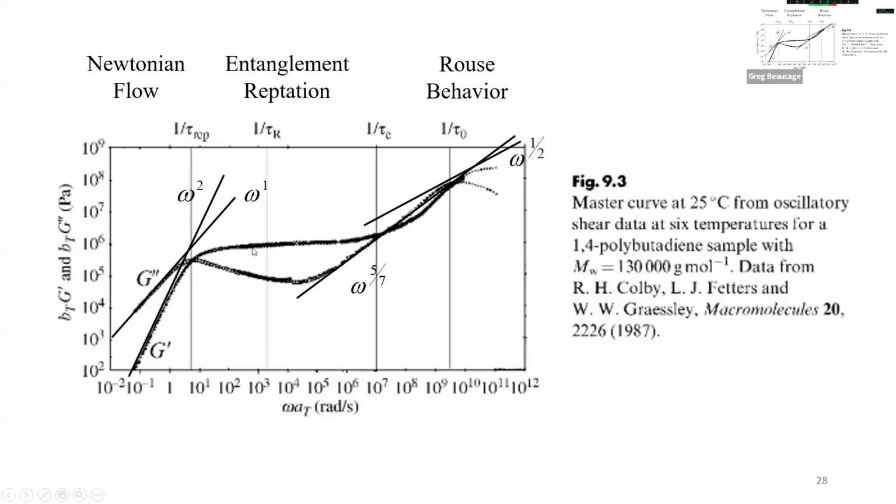And then you get to a higher frequency, and the time you reach the tau for the relaxation, then the entanglements come into effect. Before that, entanglements don't matter because they can just relax, and it's just a fluid. Then you reach that, and then you get a plateau. It becomes like a rubber, and it's got a constant modulus. The entanglements act like crosslinks. So you're at a time where the entanglements can't relax. They're actually like a physical linkage of the system and it becomes a rubber, basically, at that point, with a constant modulus that has to do with the density of the entanglements, right?